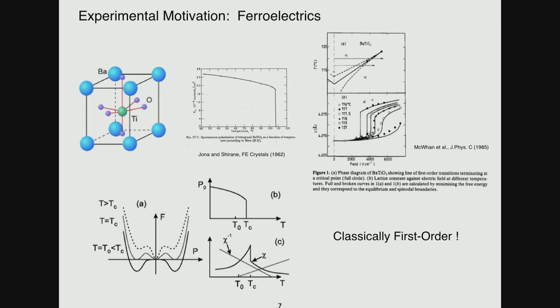Now, ferroelectrics, like this poster child ferroelectric barium titanate, are insulating materials where electromechanical coupling is crucial. And they're usually at ambient pressure, they have first order transitions. Okay, so a first order transition here, we have polarization as a function of temperature. This is just reminding us what a first order transition is. It means that we have a metastable state, we have a very sharp specific heat, polarization like this. And in fact, what was shown in barium titanate with time-dependent X-ray diffraction is that actually if you turn on a field, you eventually go out of this first order transition and you have a classical critical point.